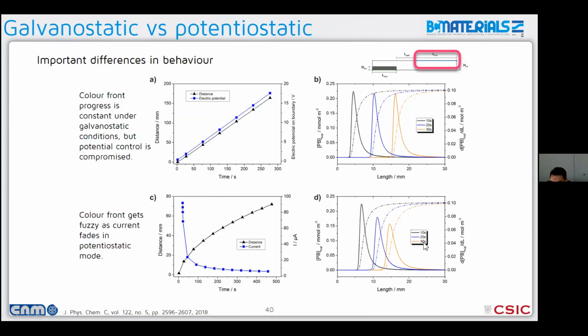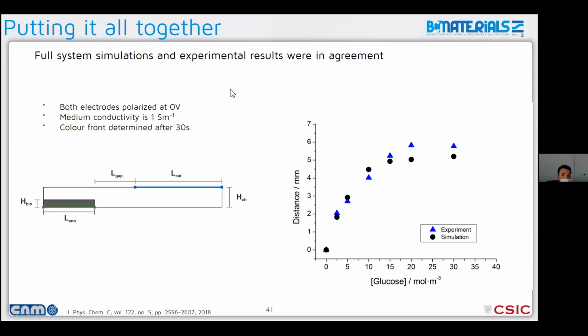So you can see at longer times you have consumed more material, so the internal resistance has increased, and then you have a broader area where, well, the color front is a little fuzzier. And then what we did was to run the model connecting both systems together and looking at the response. And again, we saw that the system responded quite well